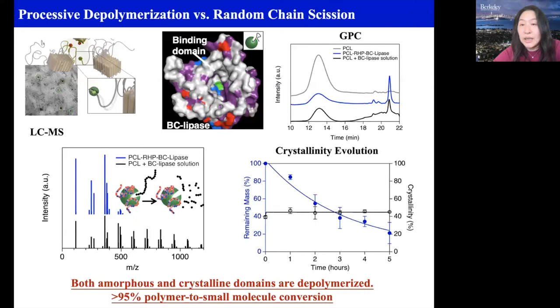So what about the part that is in the crystalline domain? A lot of times the reason we end up getting the microplastic is because the polymers in the crystalline domain are not accessible. They are held together by forming the crystal, so the enzyme really cannot get into it. In this case, we just got really lucky. It turned out that the enzyme was able to pull the polymer chain out of the crystalline domain, because once it hangs onto the chain end, it keeps chewing it. Like, you know, you have a spaghetti noodle, you just take the end until you finish that spaghetti and you jump into the next chain.